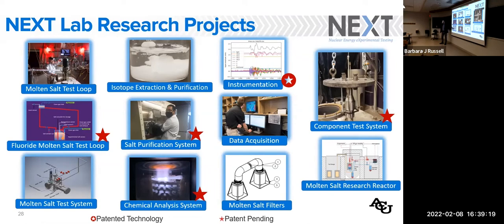Our next system will be 10 times bigger, about 50 gallons of salt. And this system will integrate a salt purification system with it. We're working on a small scale salt purification: how do you get the oxygen out of the salt in a glove box today? But we're going to build a large 50 gallon size system to pair with this molten salt system. This will be a system that hopefully is clean salt and minimizes corrosion. Whereas with these first two systems, we just put salt in and we try our best, but we understand there's going to be oxygen in there.